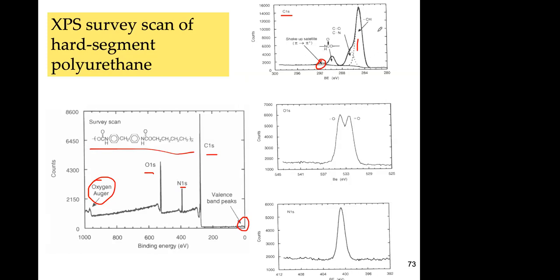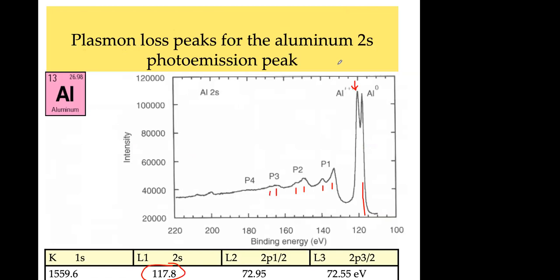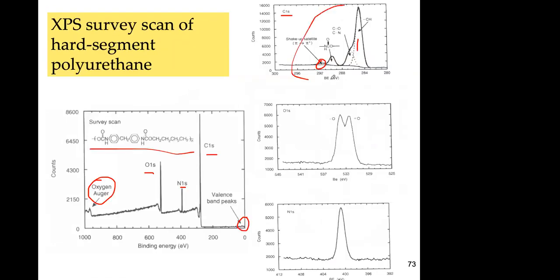So the structure of the carbon 1s can give you very nice information on the functionalities of the carbon. And here you see two carbon-oxygen peaks. This is one oxygen and this is the other oxygen. They are bonded to different things. It's basically a double bond to carbon here, and a single bond to carbon here. So you can see a difference in the oxygen 1s peak. The nitrogen is only one peak, and basically you have only one nitrogen. This one is the same as this one, so there's not much difference. So this polymer, you can really analyze it very nicely by XPS and get some information on the structure.